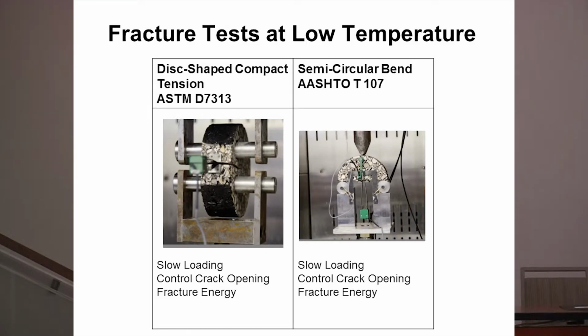Okay, as you can see, these things all involve a substantial amount of instrumentation, and so do these low temperature disc shape or low temperature fracture tests. There are two low temperature fracture tests that are used: the disc shape compact tension test, which has an ASTM standard, and then the other one is the semicircular bending test. So you take a specimen, cut it in half, and put a notch. You have a notch in the disc shape compact tension test, and what you're doing is looking at the energy that is required to propagate the crack through the material. Okay, and these are done at relatively slow loading rates, and you have to control the rate that the crack is opening.